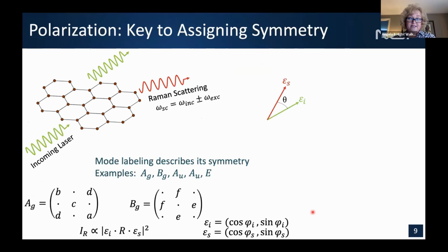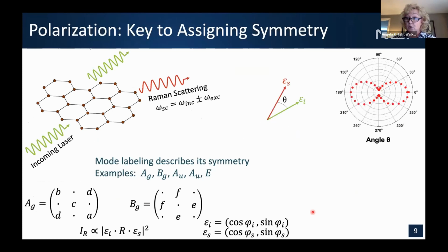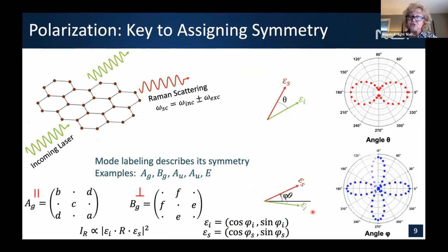As I mentioned, polarization is really important in Raman. It actually helps us to assign the different features that we see. So we have our incoming light and we have our scattered light. And we can vary the angle between those and get a polar plot, as you see here. Or we can keep those two angles the same and rotate that compared to the sample. And these two different angles allow us to fill in the matrix elements and enable us to assign the features that we're seeing. This is going to be very important a bit later when we talk about it, but it's just another strength of Raman spectroscopy.